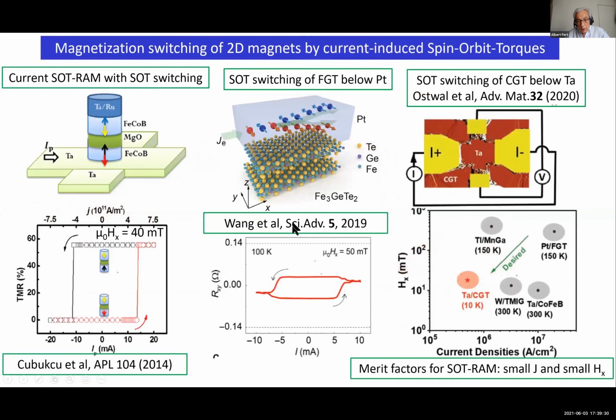But so now, what sort of application can be derived from these spin orbit effects in 2D materials? For the classical 3D materials, the classical application is what is called the SOT-RAM, spin orbit torque RAM. So this is a usual schematic picture of a SOT-RAM, that is a magnetic tunnel junction with two magnetic layers on both sides of MgO.